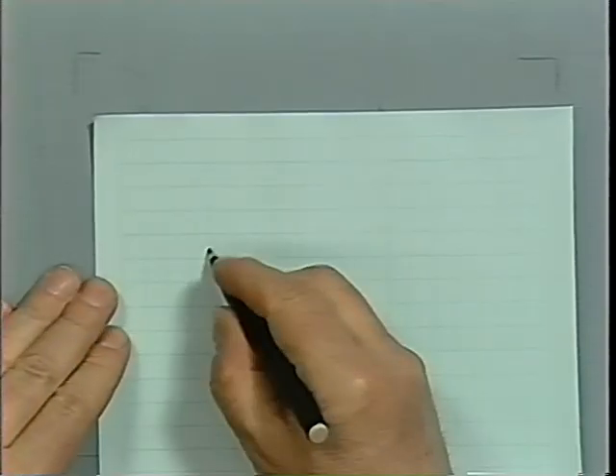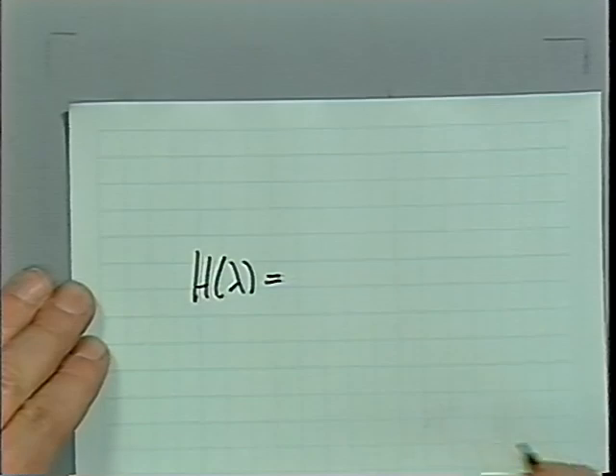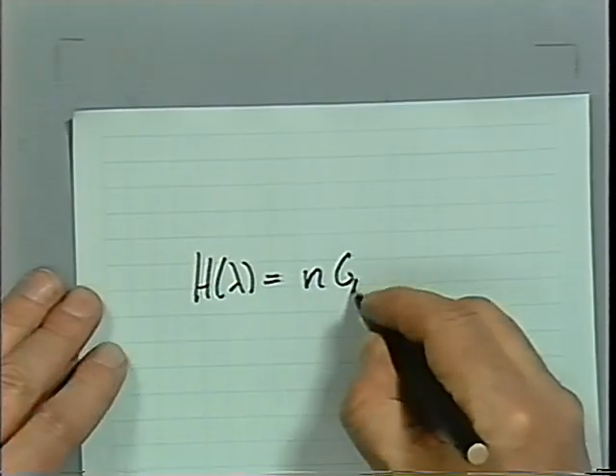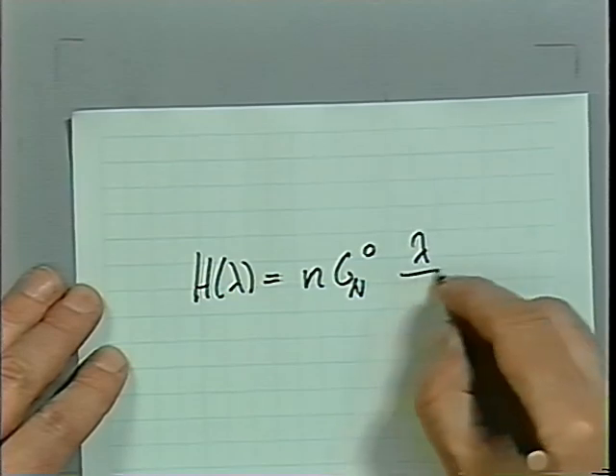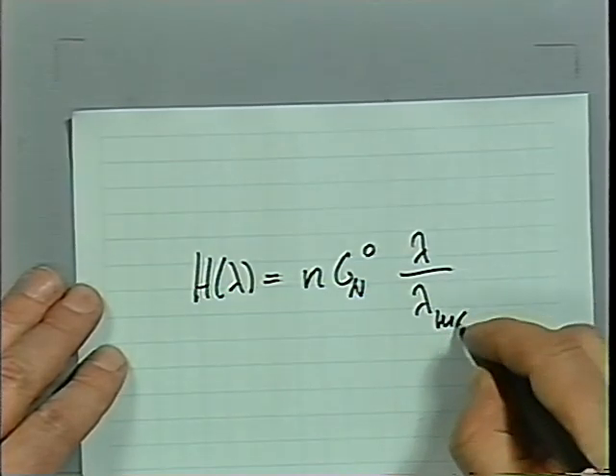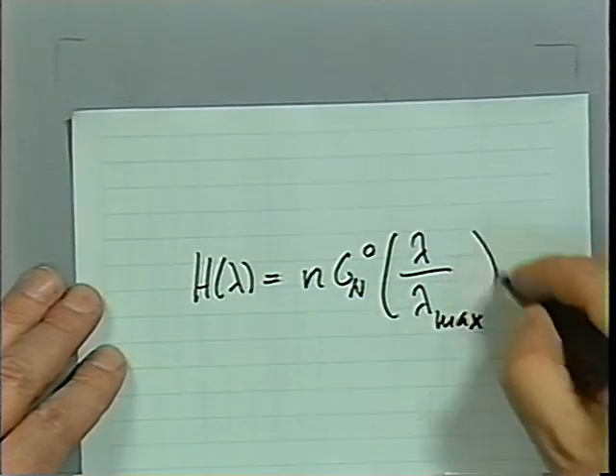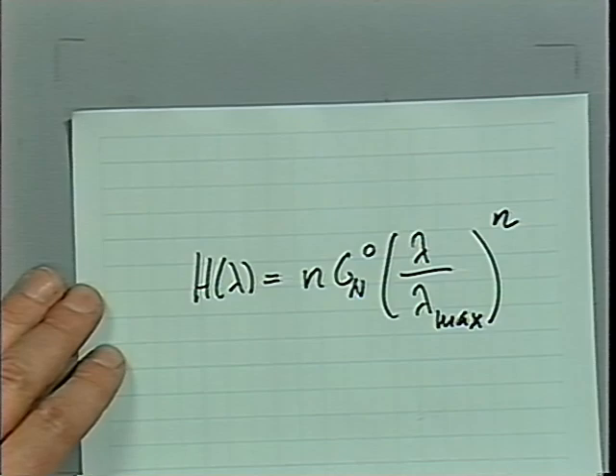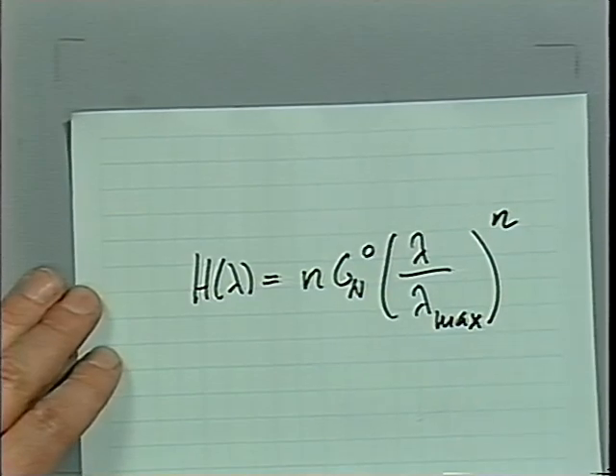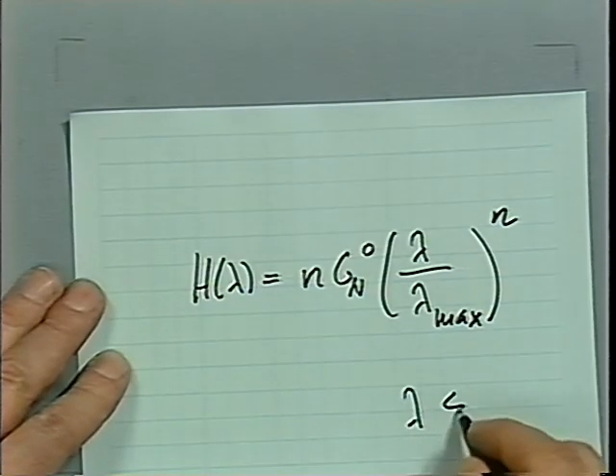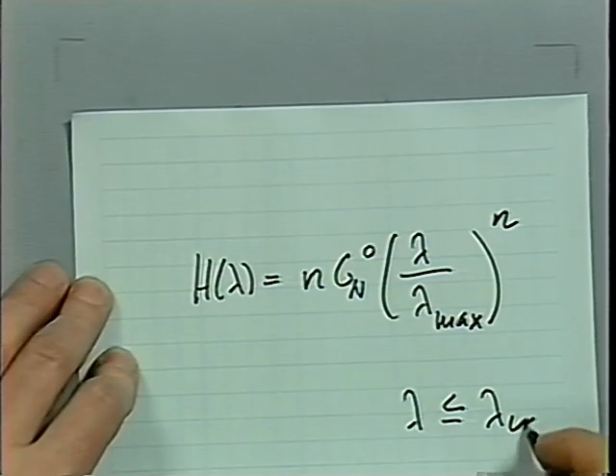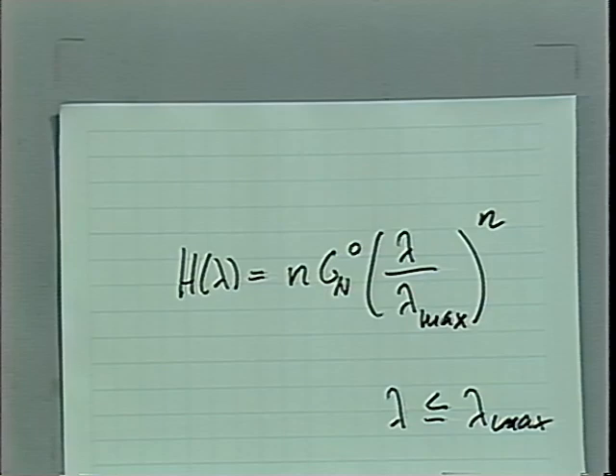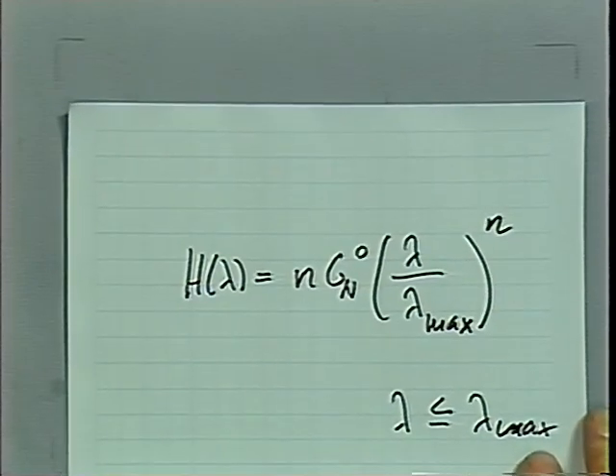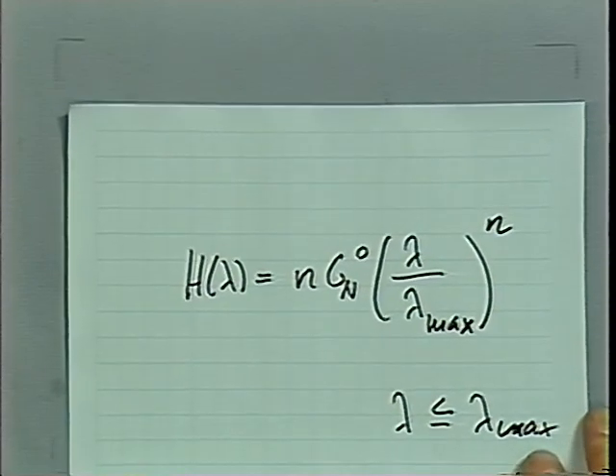We said that h of lambda was given by a constant, which is just n times the plateau modulus, times lambda over the cutoff, which is lambda max, to the n power. n in our case was about 0.2 or 0.25, in that order of magnitude. And this is valid for lambda smaller or equal to lambda max, if we neglect the glass transition behavior. Now, that is a very nice result, and it relates directly the molecular structure to the relaxation behavior.